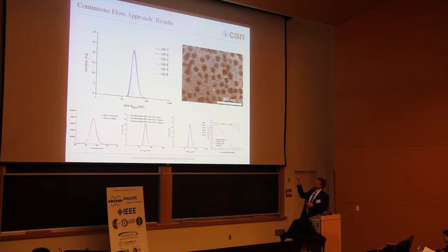If you look really close, I hope you can see it, you will find that most of the micelles contain just one particle. And that's exactly how it was designed, because it was designed for quantum dots, and quantum dots need to be encapsulated as single particles. But if you look really close, you might find that there are several micelles which contain more than one. Usually 2, and a very small amount contain 3 particles.